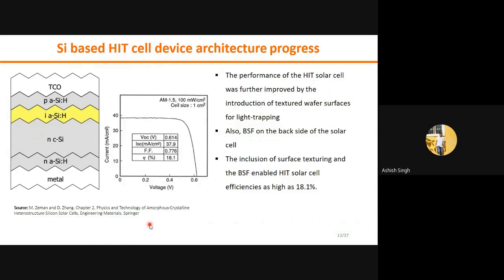So to improve the current density and VOC of the device, they took the N-type silicon wafer and textured it to reduce the optical loss from the device, put the passivation layer on it, and then the hole transport layer and the TCO. And on the back side, they made a back surface field of N-type amorphous silicon. So it will push the carriers to the front side, and it will attract the electrons for efficient electron collection. From this device architecture, they could make 18.1% efficiency, and VOC was slightly improved, 614 millivolt. Current density is 37.9, which also improved.